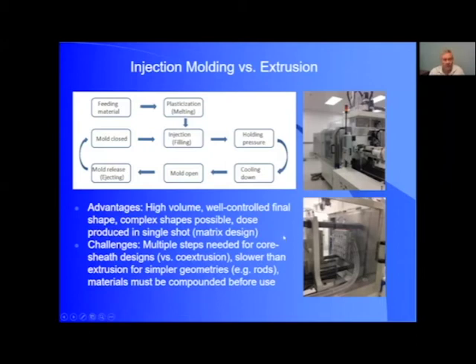various cavities that are machined into the surface of the mold. So the advantages of injection molding is that it can be very high volume. You can control the final shape, based on your molds. And basically you can make your finished part in a single shot in the case of a matrix design. Some of the challenges compared to hot melt extrusion is that you'd need multiple molding steps if you can even achieve it at all for a core sheath design, because in many polymeric implants, the sheaths are very, very thin. So co-extrusion is definitely a winner in those cases.